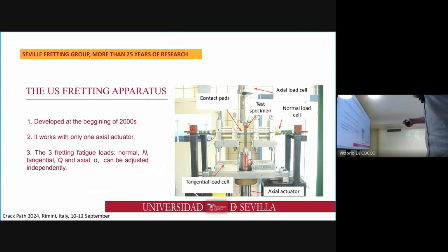Here we can see a picture of a similar apparatus, but constructed in Seville at the beginning of the 2000s. The main characteristic of this apparatus, in contrast with the frequently used fretting rig, is that you are able to apply independently the three major fretting loads: the normal load, the tangential load, and also the bulk load. This can be done moving these clampings.